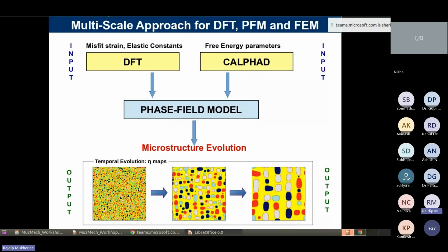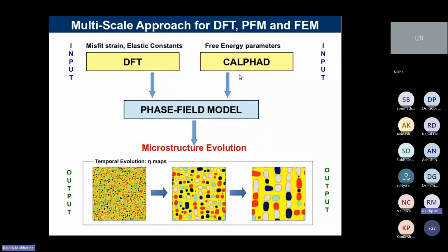You can see how we can extract the thermodynamic description of defined alloys, right? So at least for binary alloys, you can get it easily, right? So those things you can extract and use in a phase field model. So this is the basic structure of our software. That is what we are discussing, not the graphical user interface, but the backend of the software, right? So there we can calculate the misfit strain and elastic constant using atomistic calculation. We can get the free energy parameters from CALPHAD calculations, and use all these data as an input for a phase field model, which is used for microstructure evolution.